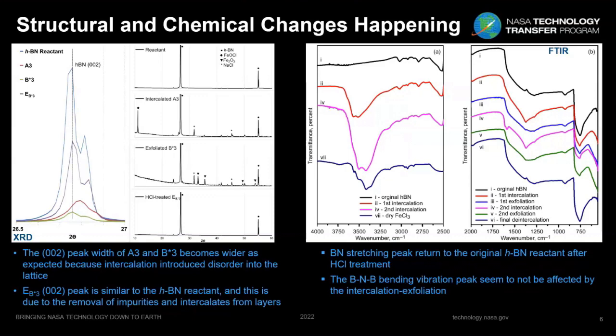In this other FTIR in the middle, you can see that the changes happening in the intercalation process are due to the introduction of iron chloride to the sample. We show at the bottom a clean, dry iron chloride, and at the top the original boron nitride, and you can see the intercalates are very similar to the iron chloride.